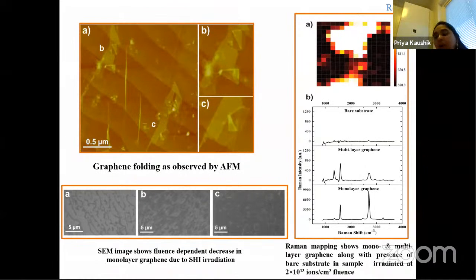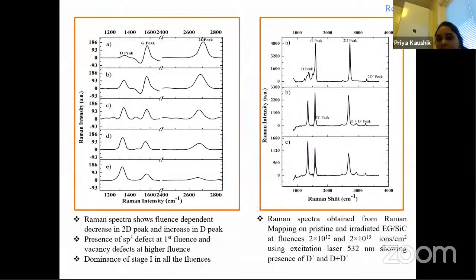So what we have done is, due to ion irradiation, the graphene got folded multiple times, which results in changing its property, which is also depicted in the Raman in B and also in the HRTEM images. Then this is the Raman, which shows that following ion irradiation, the D peak, which represents the defect peak of graphene, increases, and the G peak also decreases, and the 2D peak also decreases. So following ion irradiation, the D peak increases, and the G peak and 2D peak decrease.